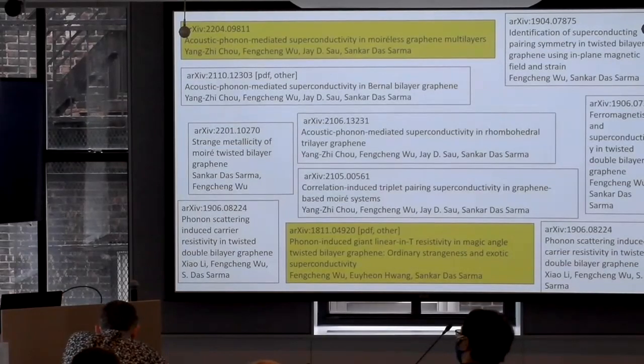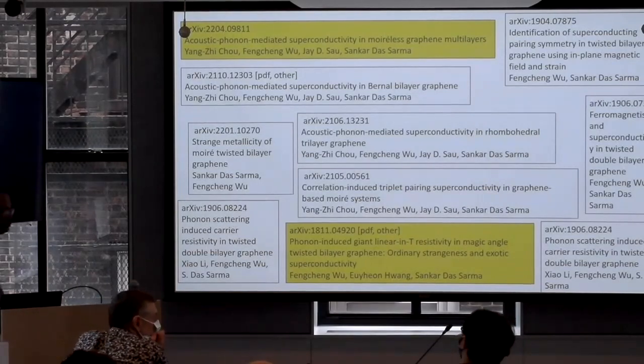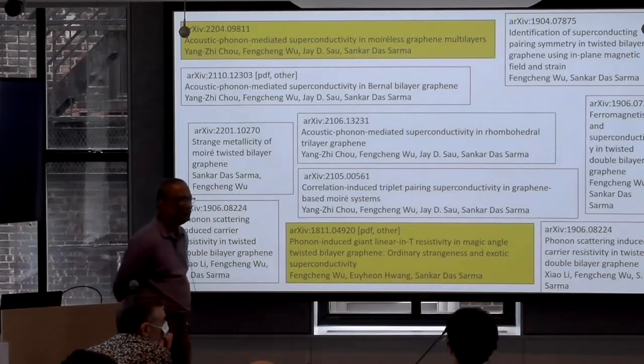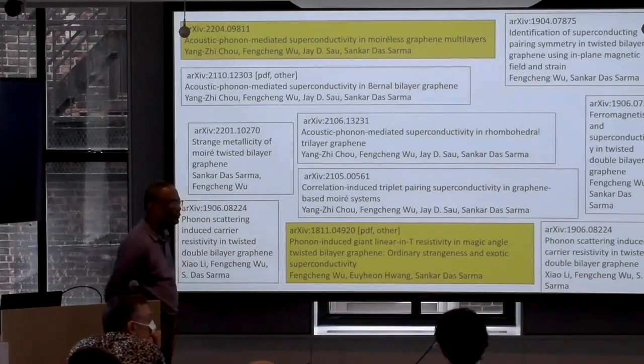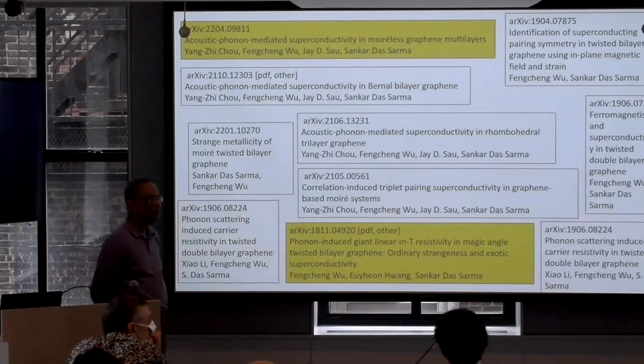That's all I'm saying. May I make a point about perhaps purity of samples? Yes. If you look at the theoretical calculations, every linear resistivity, everything that gives you a linear regime, if you extrapolate that to zero temperature, you get a strongly negative intercept. Yes. And every measurement in both graphene and correlated materials does not have that negative intercept. Correct. The question is, is that simply a disorder offset that's pushing things up, or is there something else?